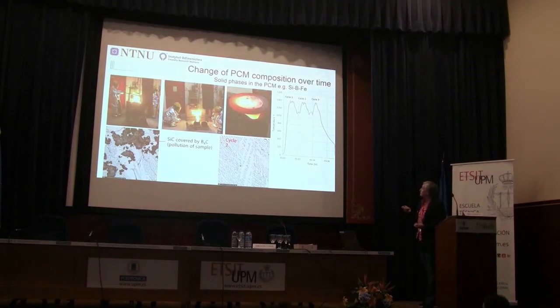Another example: here we are putting this iron alloy into the crucible, the prototype crucible, and we also did some cycling of this material. What we want to see after some cycles is a nice eutectic structure that hasn't changed composition over time. However, if it's reacting with the equipment, for example, here in one experiment, we had some polluting carbon, probably some dust falling into it. So we see that we get a lot of silicon carbide.